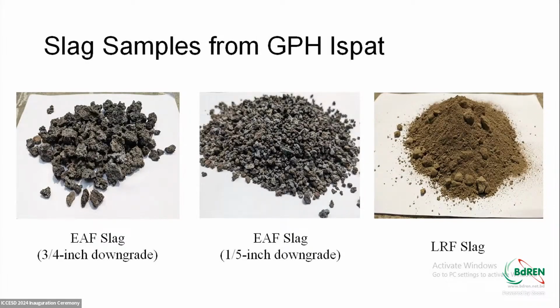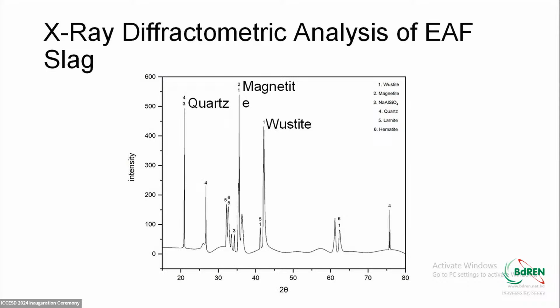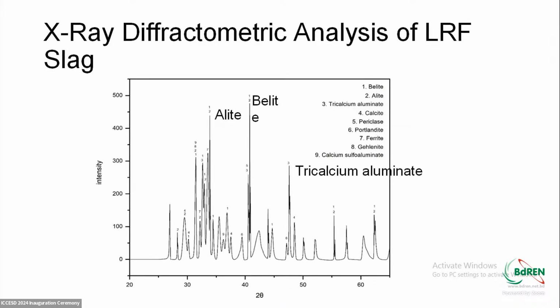We collected the slag from GPH Ispat; the collaboration was with GPH Ispat. The electric arc furnace slag was crushed in different sizes, like 3/4 inch downgrade and 1/5 inch downgrade, and LRF slag was collected in powder form. We used XRD, and found that for electric arc furnace, a great portion of its component was iron oxide, like magnetite, wuestite, and some silicon oxide. We'll show other components too.